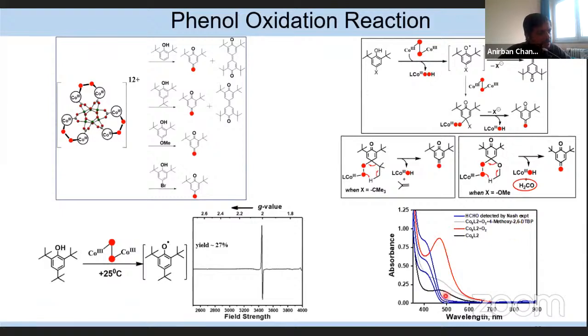So here, I would like to explain that this black spectrum is for the starting cobalt complex, whereas this red one is for the cobalt peroxo species. When the reaction was done with 4-methoxy-2,6-di-tert-butylphenol, this spectrum decays to this gray spectrum. Then, into this solution, when I add the NASH reagent, I find a band generating with increasing temperature at 413 nanometers, which confirms the presence of formaldehyde.